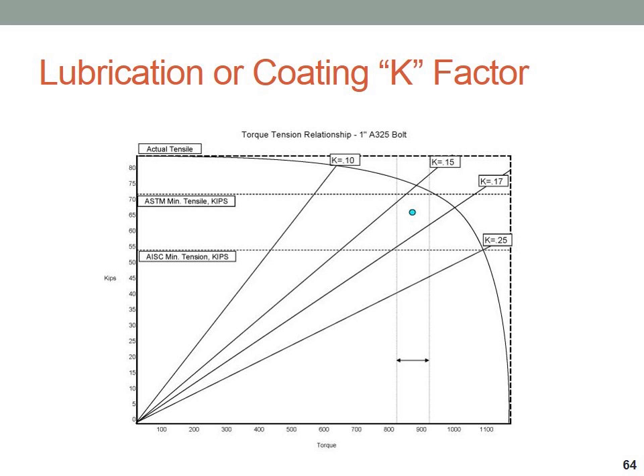Another way of looking at this is decreasing friction or increasing the effectiveness of a lubricant decreases the effect of torsional stress on a fastener. And torsional stress can cause fasteners to fail at a much lower level than they would without that torsional stress. And a good way to look at that is, here's an example of a 1-inch A325 bolt. This is the AISC minimum design tension for that size and grade. This is the minimum tensile strength.